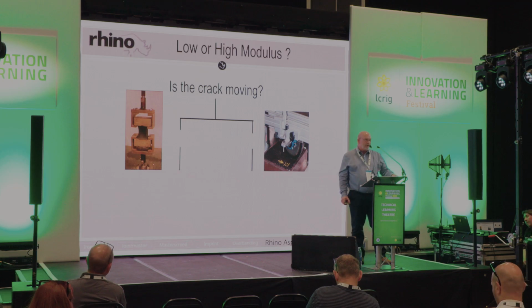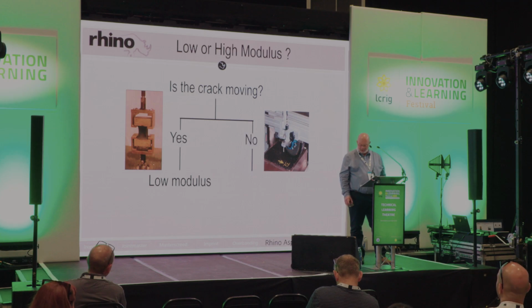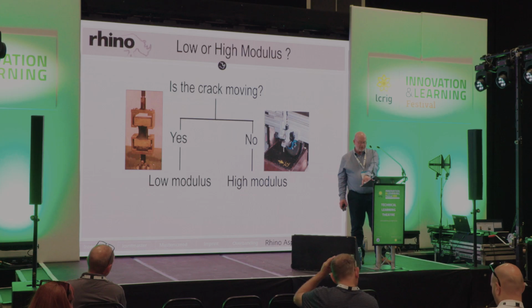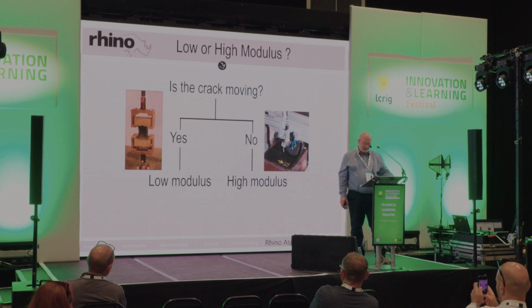Well, is the crack moving, for instance? If it's a concrete subbase, then yes, the crack will be moving because of thermal expansion and contraction, in which case you'd be selecting a low modulus material. Alternatively, if it's something like a ravelled lane joint, it's likely that it'll be no, in which case you'll be selecting a high modulus material, which is a stiffer material and can withstand a lot more wheel tracking.